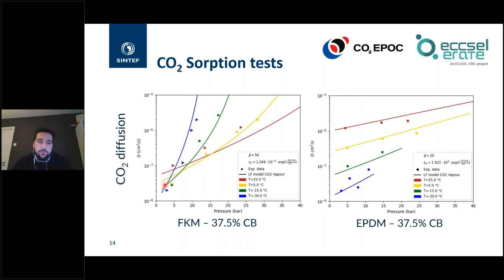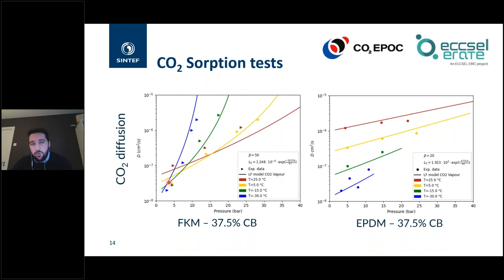CO2 diffusivity tests are very interesting. For FKM, the diffusivity is significantly impacted by the CO2 content in the polymeric matrix. In the EPDM case, as expected, the diffusion coefficient drops significantly at lower temperature — behaving quite ideally. But for FKM, because of the very high solubility, swelling phenomena occur to a significant extent, impacting how CO2 diffuses out and actually increasing the CO2 diffusion coefficient at lower temperature — a quite peculiar result.